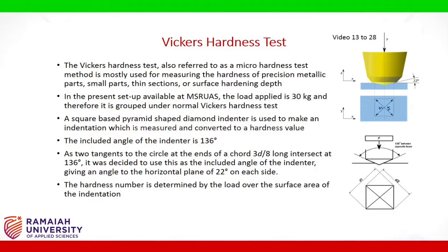As two tangents to the circle at the ends of a chord 3d by 8 long intersect at 136 degrees, it was decided to use this as the included angle of the indenter, giving an angle to the horizontal plane of 22 degrees on each side. The hardness number is determined by the load over the surface area of the indentation.